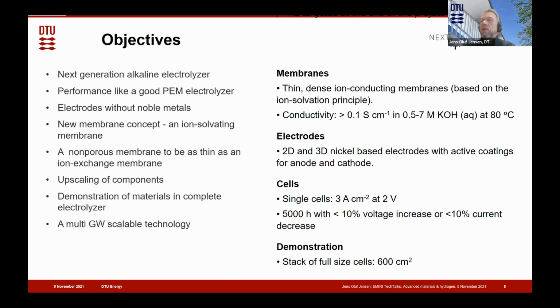For the single cell, we have a target of 3 amperes per square centimeter at 2 volts. It's possible that it will be operated at a lower voltage that will be desirable for sure, but that's just an easy benchmark to see what is the current at 2 volts. And we'll demonstrate 5,000 hours with less than 10% degradation, either measured as a voltage increase or a current decrease.